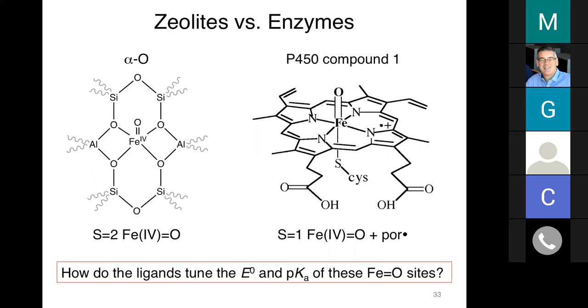So in this way, nature kind of cheats. It gets a favorable reduction potential based on the favorable reduction of the porphyrin radical. And then it's able to have a favorable pKa through strong donation of these ligands into the iron center. So in this case, nature has kind of divided the problem up into two pieces and solved each of them independently, which I always thought was a very acute solution to this problem. Any questions about that before I move on?